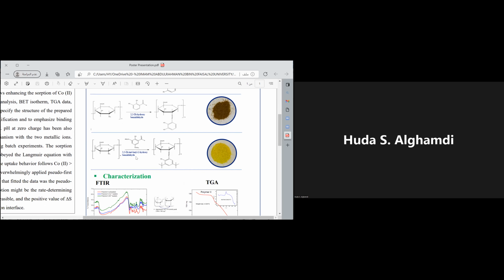The last one is 3,5-ditertiary-butyl 2-hydroxybenzaldehyde. We added it to the matrix of Chitosan, so the carbonyl group inserts into the NH2, and we achieved the imine group, as you see here. Why we chose this monomer? Because we thought that maybe the tertiary butyl groups here will induce the lone pair of electrons, and that may catch the metals very well. But what happened here is the second polymer gave me a strong and stable complex with the metal ion.